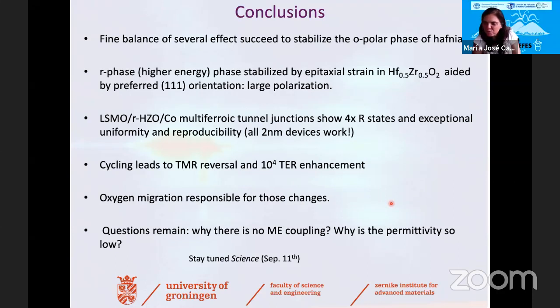Akash Bhatnagar asks, is there information regarding the number of voltage cycles before fatigue sets in? Yeah, that's a good question. I didn't say anything because it depends very much on the surface of our devices. Our devices are 30 microns by 30 microns, but we also tested 10 microns. The number of cycles that they can withstand until they fail depends very much on the surface area, and it goes from a few tens to 100, depending on the material. But that is not optimized yet.